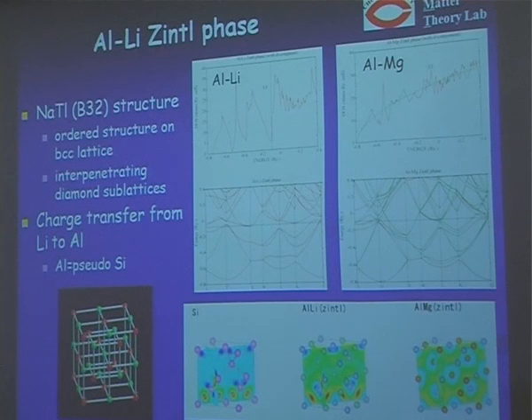And the Zintl compound is the aluminum-lithium Zintl compound. It's a very simple structure, which has the sodium-thallium structure. And this structure is an ordered structure on a BCC structure. And it is interpreted as interpenetrating diamond sublattices. If we assume the charge transfer from lithium to aluminum, because aluminum is more electronegative, then aluminum has 4 valence electrons. So that means aluminum looks like a pseudo-silicon atom. And this pseudo-silicon atom is placed on a diamond lattice. So the total electronic structure is expected to be very similar to silicon diamond.